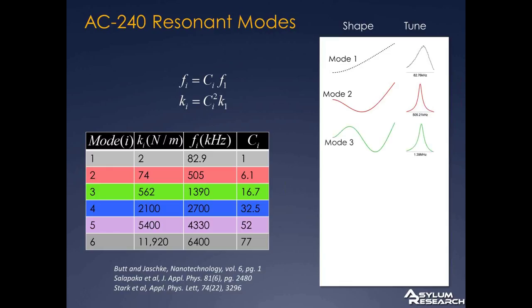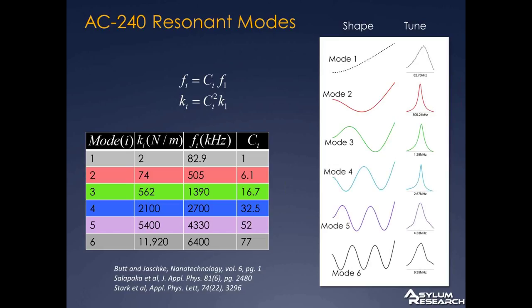The third mode looks like this, the fourth, the fifth, and the sixth. And you can see the frequencies go up. I've shown measured tunes, so 1.4 megahertz, 2.7, 4.33, and 6.35. Now, the thing that's interesting to notice about this, and we'll get back to this at some point, is that the stiffness of these modes goes up like this number squared. So this sixth mode, for example, is considerably more stiff than the first mode.